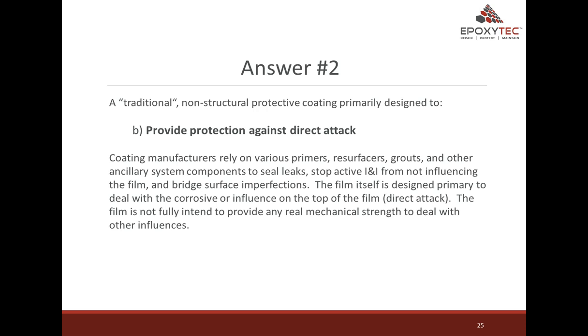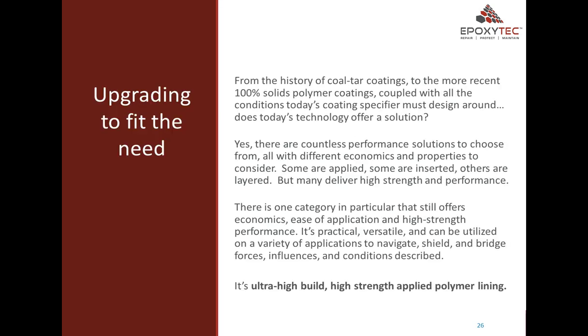The answer is B. Traditional coatings provide protection against direct attack. Coating manufacturers rely on various primers, resurfacers, grouts, and other ancillary system components to seal leaks and stop active I&I from influencing the film and to bridge surface imperfections. The film itself is designed primarily to deal with the corrosion or influence on the top of the film, direct attack. The film is not fully intended to provide any real mechanical strength to deal with other influences.